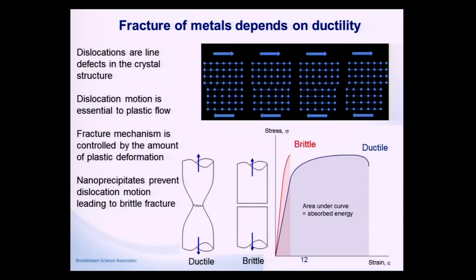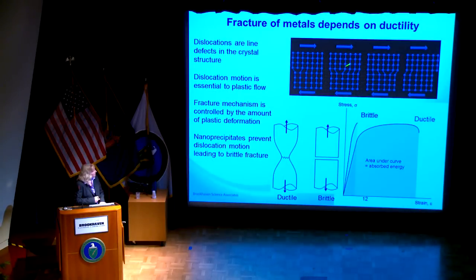I'd like to now describe why the damage is so severe to pressure vessels. Fracture depends on the ductility of the material. The mode of fracture in a material depends on the ductility, and this is controlled by line defects in the material known as dislocations. You can see a dislocation here. It's an extra line of atoms in the material, and this allows the material above and below to slide past each other, so the material can deform. This is a deformation mechanism in the material, and this is a good thing in steel, because you want the material to deform before it breaks. With ductile failure, you'll get a large amount of deformation, and you'll see necking before it breaks.